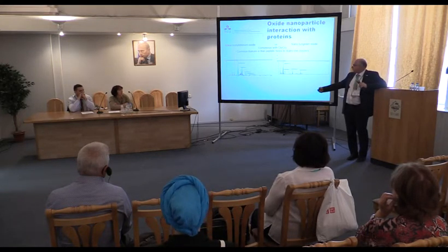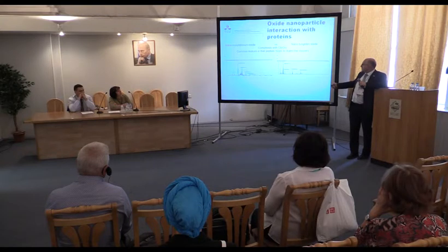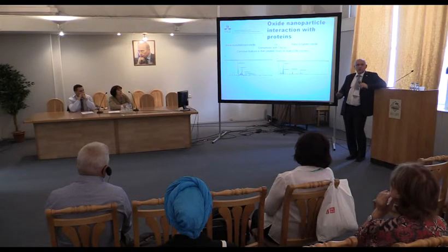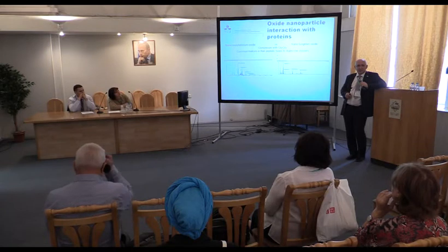So what we can see here, we can see hexamolybdate, and we can see beta-octamolybdate and tungstate, and you can see, of course, some remains of the original bigger particle. But not much. In the case of molybdenum, almost nothing. In the case of tungstate. So the interaction is not one way. It's not only what particles are doing with biomolecules, it's very much also what biomolecules are doing with particles. And in many cases, biomolecules are capable of cutting the particles into small molecular species, which can have quite different reactivity. And this we will be working on further with our colleagues at ITMO, because this is very exciting.